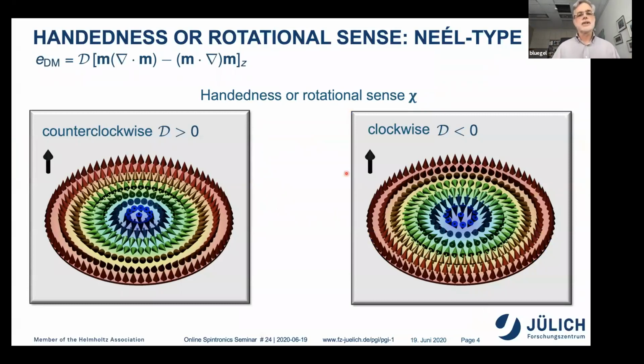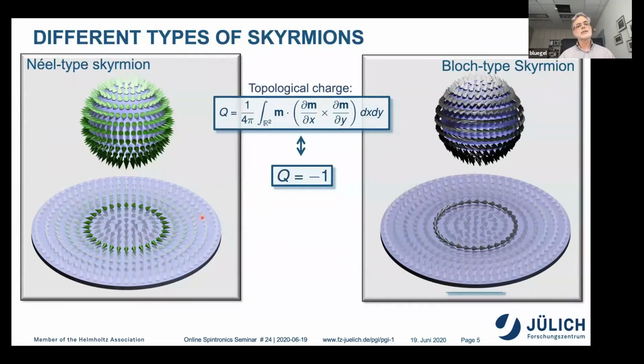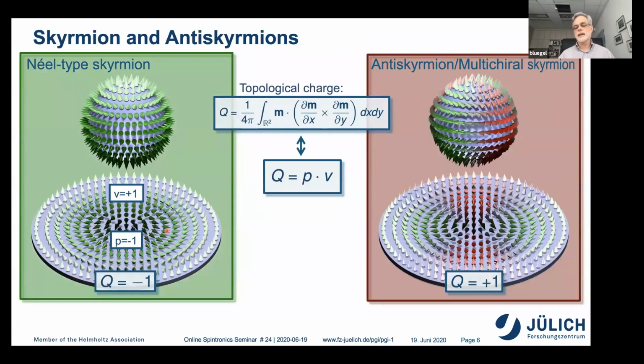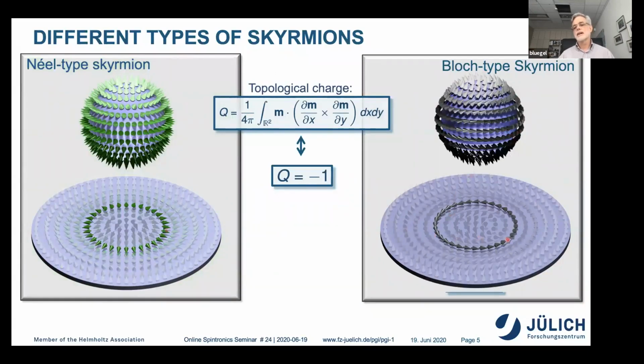So we have skyrmions which have different handedness. We have counterclockwise skyrmions, for example, here. You see from the inside to the outside along the radius, the magnetization rotates counterclockwise, while here, for example, it rotates clockwise. Then we have Néel-type skyrmions and we have Bloch-type skyrmions. Both of them have the same topological charge. In my notation, it's -1. That means you know by now that there is a smooth transformation which gives you somehow from this Néel-type skyrmion to the Bloch-type skyrmion. And the difference is basically that in the Néel-type skyrmion, the magnetization rotates in a plane of radius and z direction, whereas in the Bloch-type skyrmion, it's in the direction